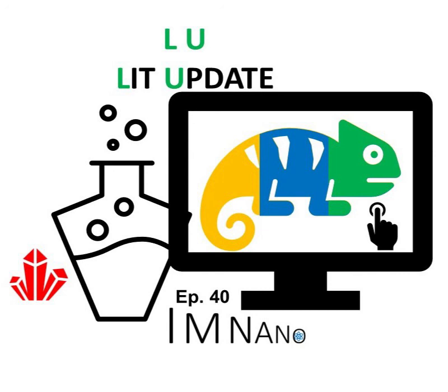And in today's lit update, researchers from Kent State University showcase the electrical, optical, and electro-optical studies of a ferroelectric nematic LC material doped with commercially available chiral dopants. Yes, exactly. And I know it's a mouthful, but this research is very important because the fast switchable reflection color at low electric fields has potential applications for liquid crystal displays without a backlight, smart windows, shutters, and also e-papers.